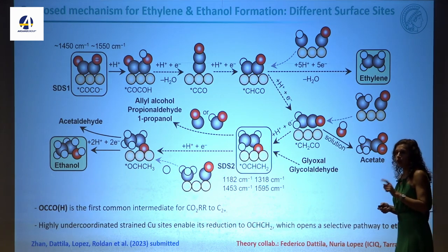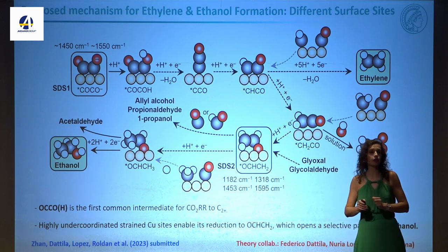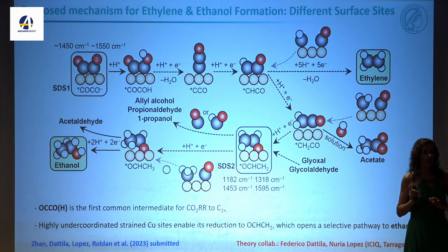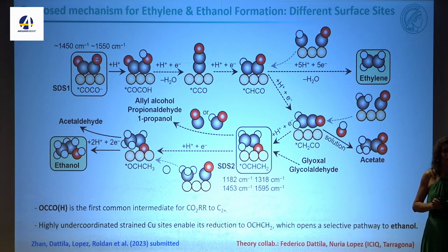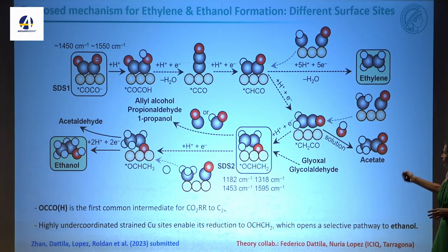Experimentally, now we don't only detect CO, we can detect this here, this intermediate, we can detect this here. And looking at the bond lengths, we can even infer whether we are going this way, again, or we are going this way. And this depends on the structure of the surface, and not on the initial structure, but on the structure that forms under reaction conditions. And we make both at the same time, so it's not one or the other. It's different sites will be making this preferentially or this.